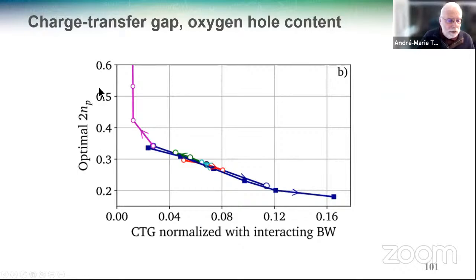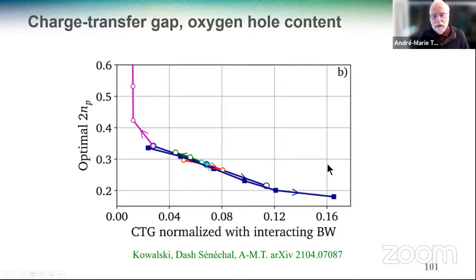If you plot the optimal hole content here, so the value of the hole content at optimal doping as a function of the charge transfer gap, you see that the two are basically correlated in both the ionic and the covalent model. And all that means is that when you have a smaller charge transfer gap, when you dope in the oxygen band, it's related to the value of the charge transfer gap. So there are more holes with a smaller charge transfer gap. There are more holes on the oxygen. Okay, so it all comes together. It's only one and the same phenomenon.